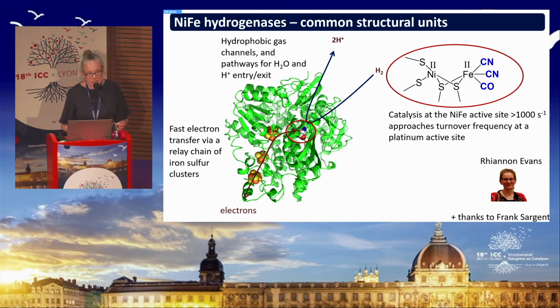What's really impressed chemists is the fact that nature has found a way to use nickel and iron for activation of hydrogen at turnover frequencies that rival platinum. Of course, the enzyme has only a single active site within the protein structure, and you can think of this as a nanoparticle catalyst. The enzyme has a diameter of about 5 nanometers, so it's really a nanoparticle catalyst, but with just one active site finely tuned and buried inside this protein framework. Of course, a platinum nanoparticle of a similar size would have many active sites on the surface, so it doesn't do so well on a sort of activity per volume basis.